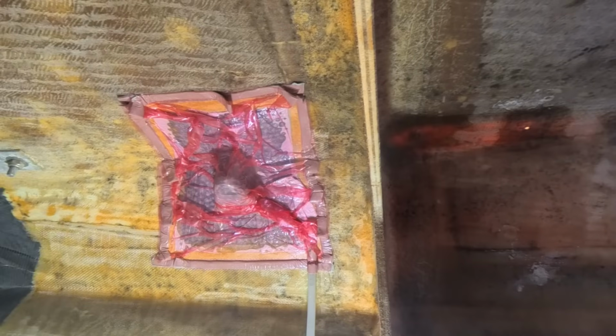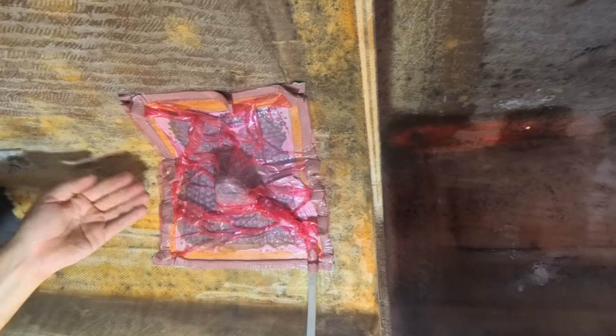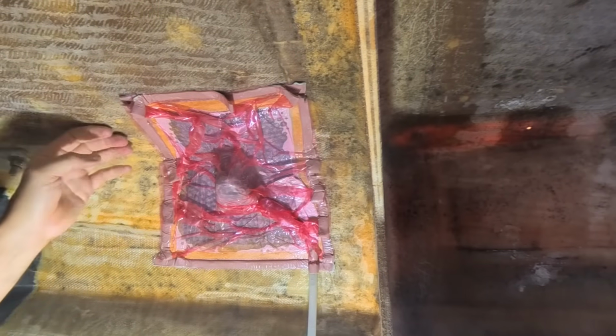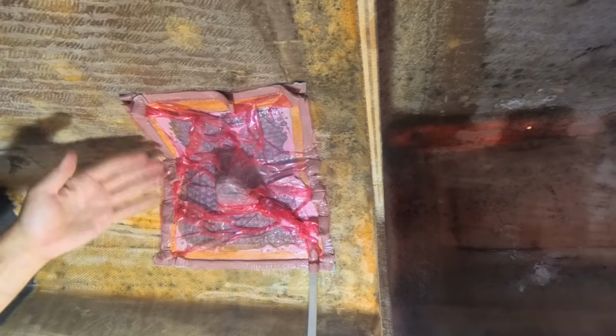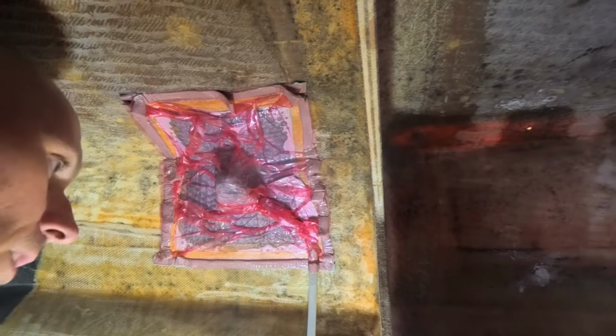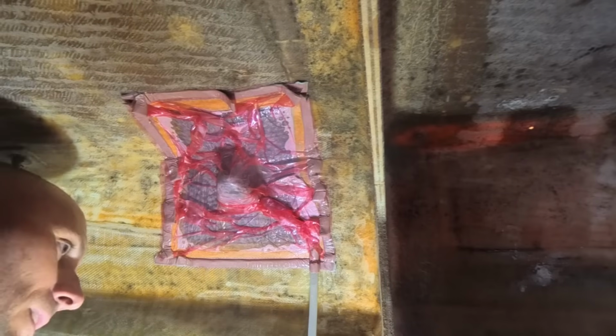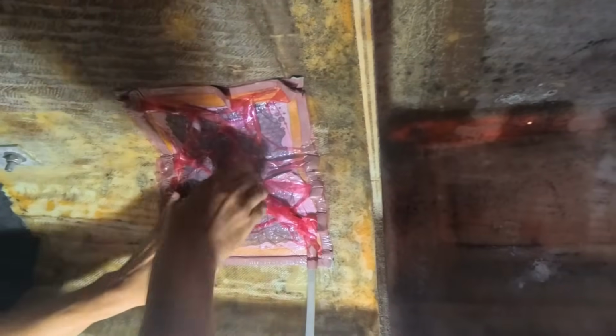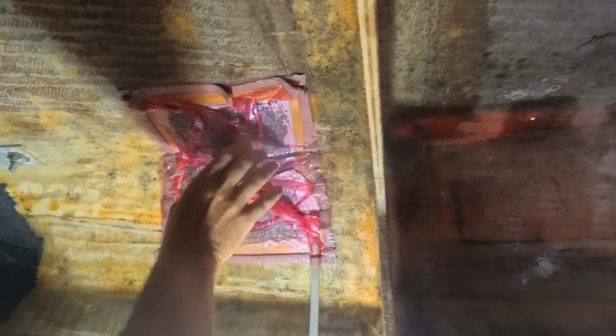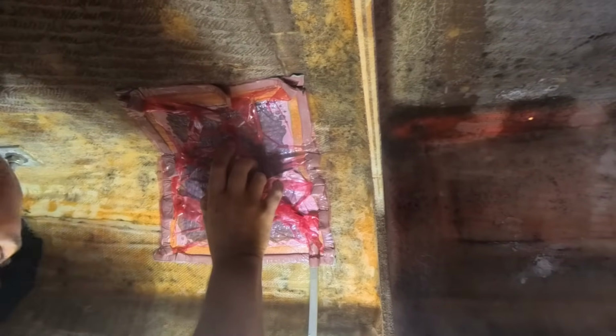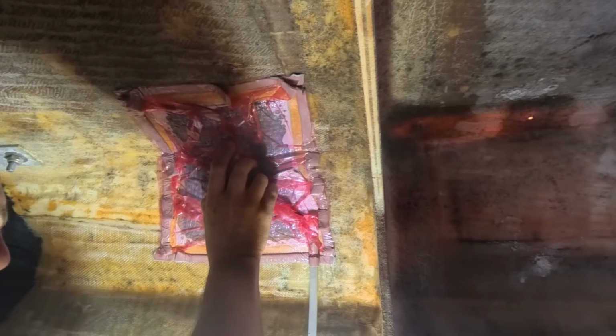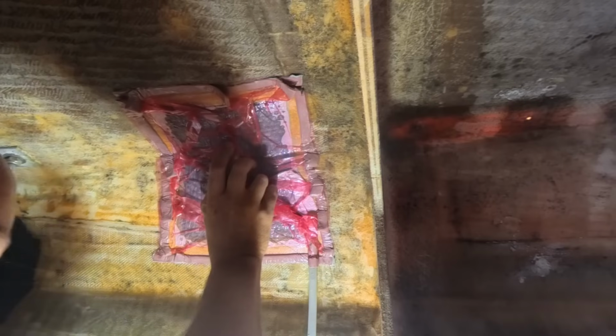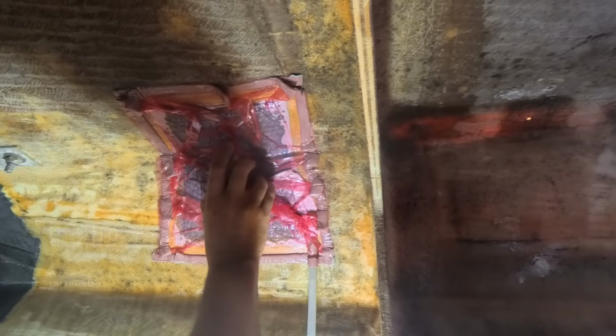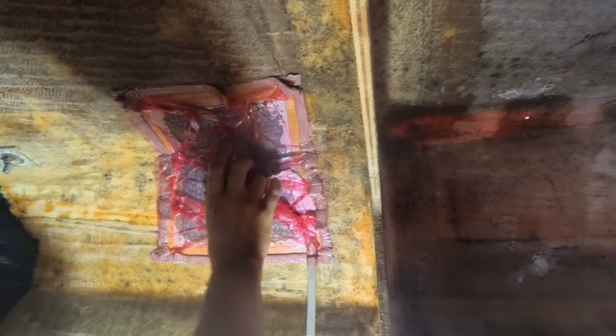So it's 30 odd degrees outside. So the laminate, the actual boat that I'm laminating to, is fairly warm. The air inside is a little bit less because we have got the air conditioner going, but you can see it's pretty warm in here. I'm still sweating. But yeah, this resin is not exotherming. It is, yes, it is exothermic because it's getting warm, but it's not got a runaway exothermic problem.